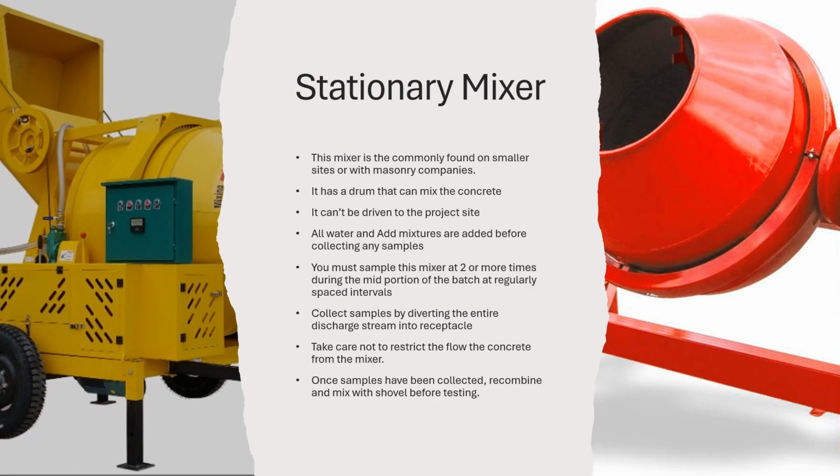You must sample this mixer at 2 or more times during the mid portion of the batch at regularly spaced intervals. Collect samples by diverting the entire discharge stream into the receptacle. Take care not to restrict the flow of the concrete from the mixer. Once samples have been collected, recombine and mix with a shovel before testing.